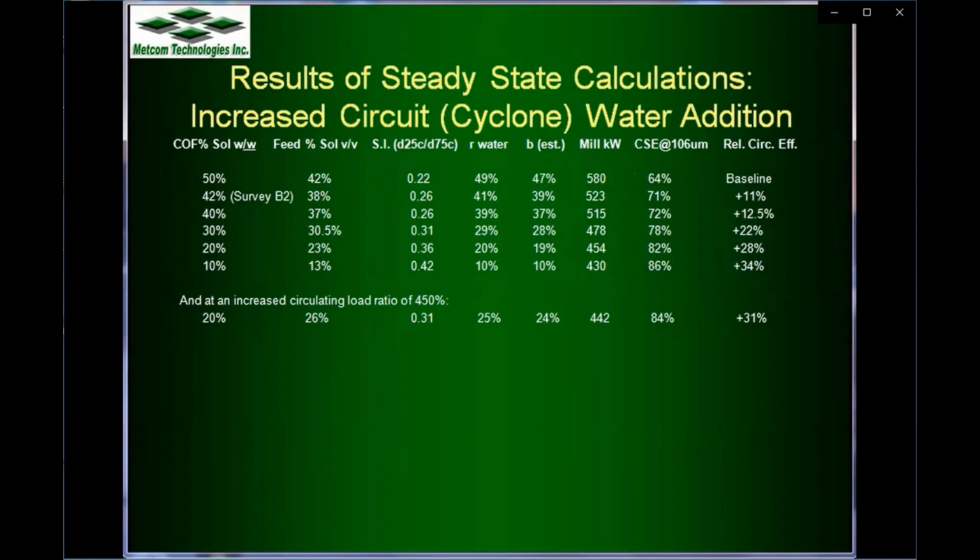This showed us that by installing a thickener after the grinding circuit, for example, to deal with all the extra water ahead of CIL processing, the efficiency of the grinding circuit could be increased by approximately 30%. The thickener was installed, and the grinding circuit significantly outperformed all previous production.